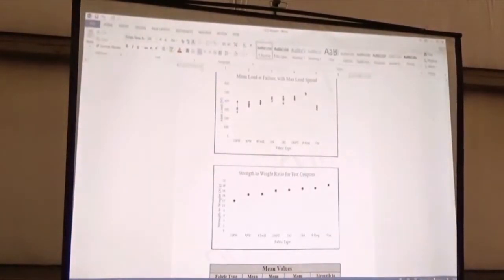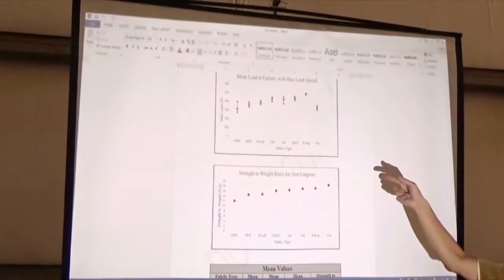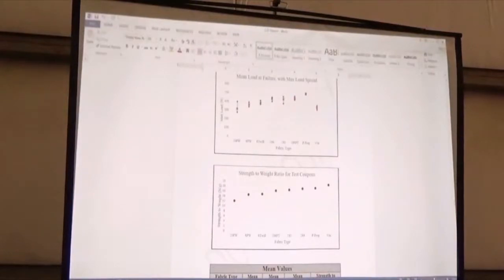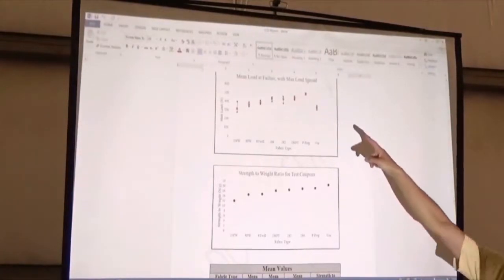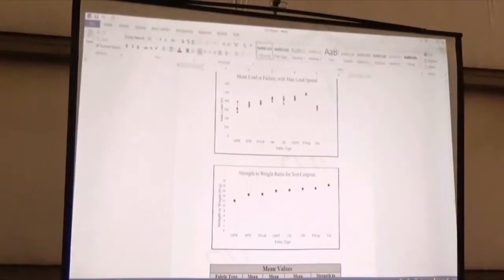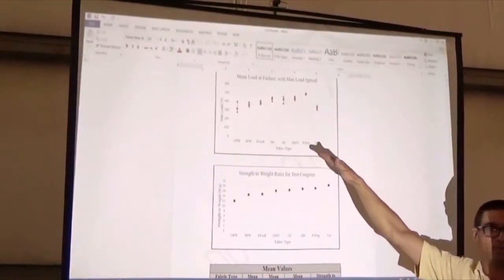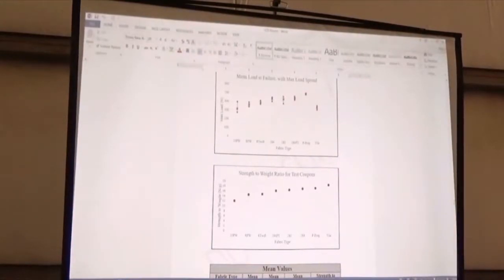So I think that's super cool, because that's indicating that no matter how good you are with, I mean, I've made a lot of these coupons. I think I do an okay job, but I cannot match pre-preg in terms of getting a consistent resin distribution, and that's what you're seeing right there. Because any kind of a failure that you get, that's because 1 or 2 fibers in that coupon did not have enough resin as the surrounding areas, and it cracked. And once it goes, everybody else around it goes as well.